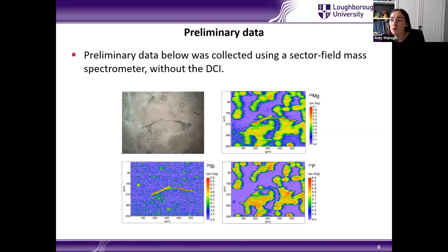Now I mentioned that our preliminary work involved sector field technology. Sector field instrumentation is what we've got at Loughborough University. So all of our method development work was done on that. We took some positives from this method development work. And the first positive was that we can actually see the fibers within the sample. We are able to get sufficient spatial resolution to see these tiny fibers, which you can see outlined here in our microscopic image. And you can see here that we're able to measure magnesium, phosphorus, and silicon, and we're able to see clear signals from those fibers. So this was a positive to the work.